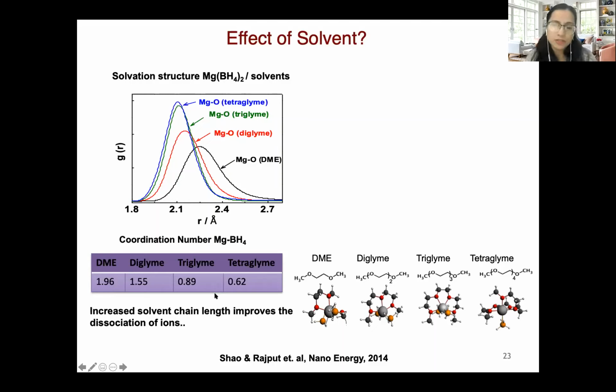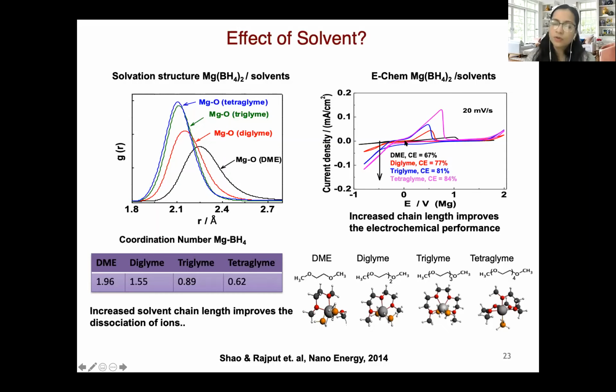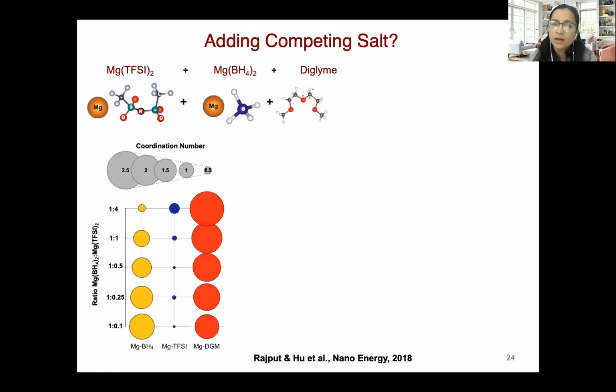And the effect of this change in solvation structure was observed on the electrochemical performance, where we found that there is a monotonic increase in the Coulombic efficiency as we are increasing the chain length of Glymes. So by just simply increasing the oxygen denticity of solvents, we were able to enhance the electrochemical performance of magnesium salts. Another simple strategy we adopted was to mix competing salts.